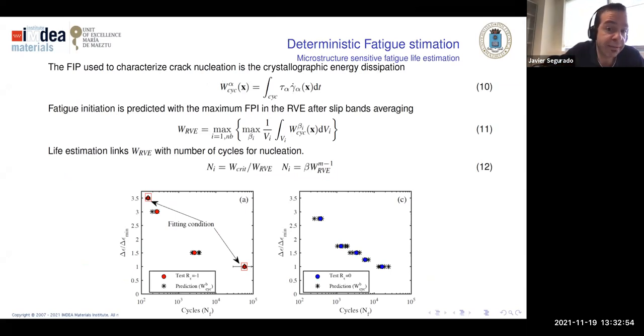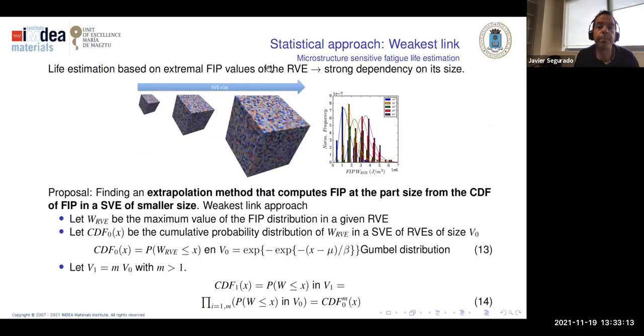Okay, and then if we have that, we can predict life, and this is good, and we have this type of predictions. This is very interesting, but some statistics is missing here. And not only that, if we follow this, you can think that if we use a much larger RVE, then the probability of having a very badly oriented grain increases. So the problem of the deterministic way of doing this is that it strongly depends on the RVE size. That is artificial, because the RVE is something that we choose.